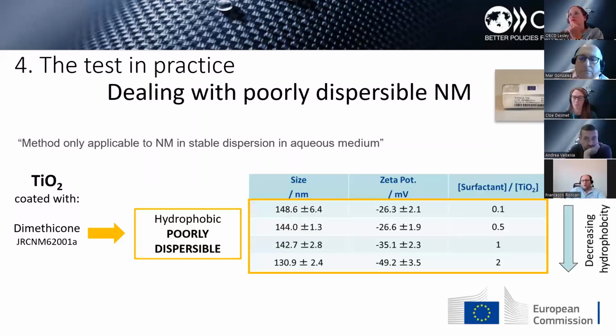But during different comment rounds together with different experts, we were able to introduce also the characterization of the hydrophobicity index of very hydrophobic nanomaterials that are, per definition, poorly dispersible in water. Here I will present the example of titanium dioxide with dimethicone coating, which is really hydrophobic.